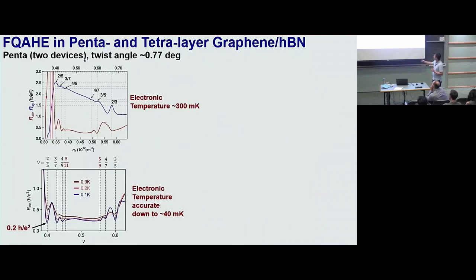Okay? So this is the data I just showed you, and at that time we didn't have good filters in our dilution fridge. So the electronic temperature at that time was probably like 300 millikelvin. Now we think we can get to something like 40 millikelvin because there's some superconducting state in graphene. The transition happened around 40 millikelvin.